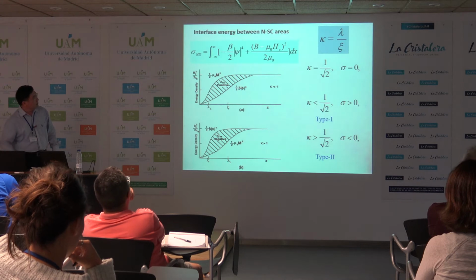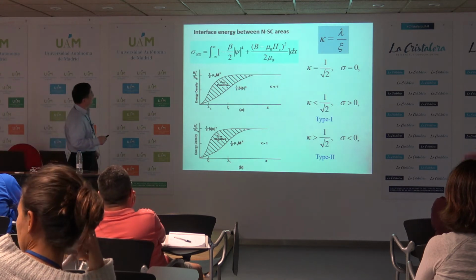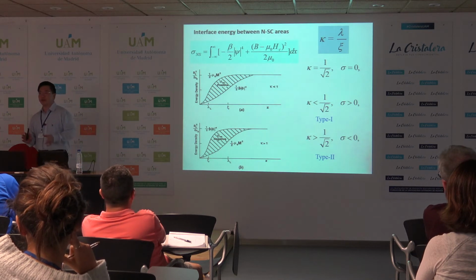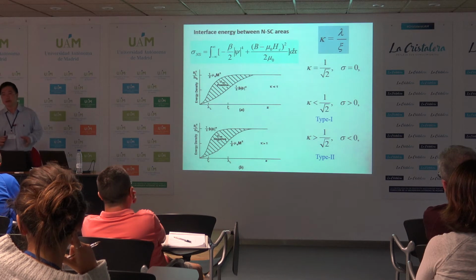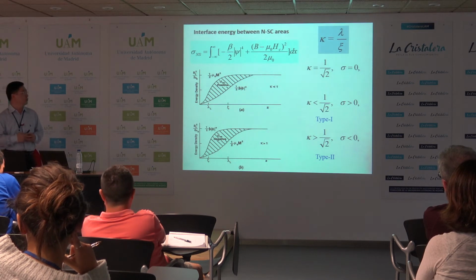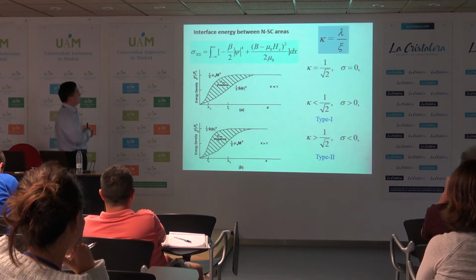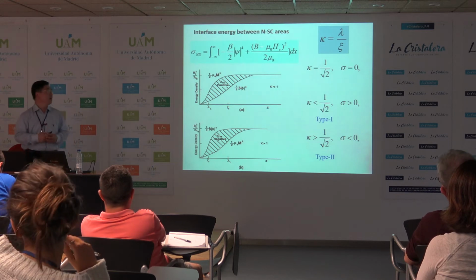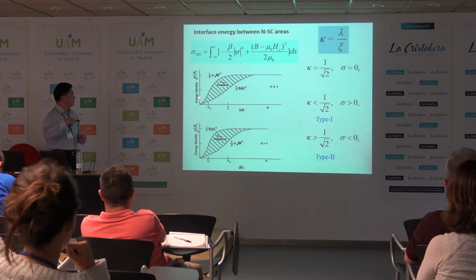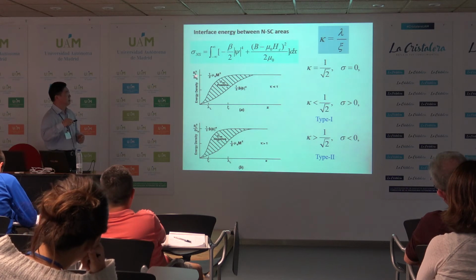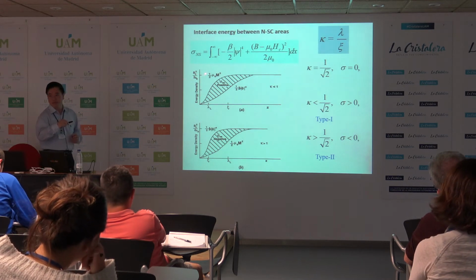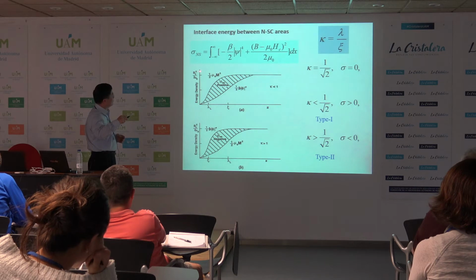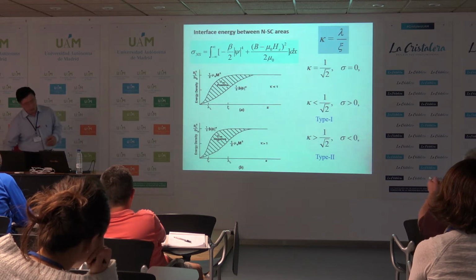And if, in a superconducting state, we apply a magnetic field, we know that the current on the edge will accumulate gradually with the field, to a certain value, then the pressure is too large. So in that case, the superconductor does not like that, and then allows the magnetic field to penetrate into the superconductor and to form some kind of a boundary. So this side is superconducting, this side is normal. But the normal with a magnetic field, because it's under magnetic field, okay? So in that case, one can calculate using the Ginzburg-Landau equation, majorly the first equation.